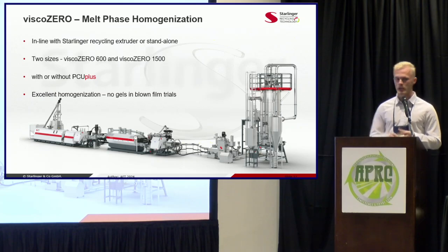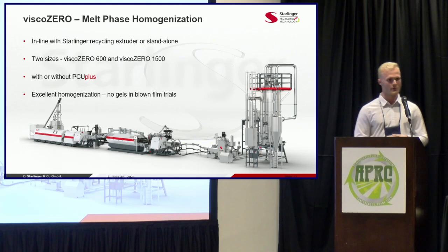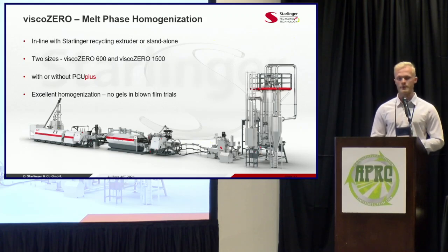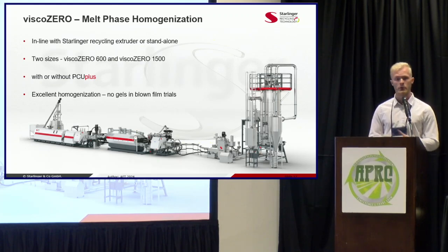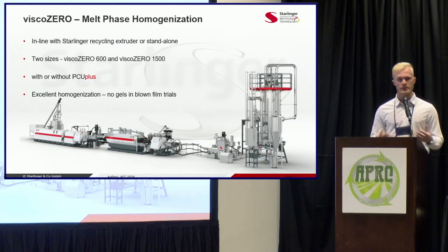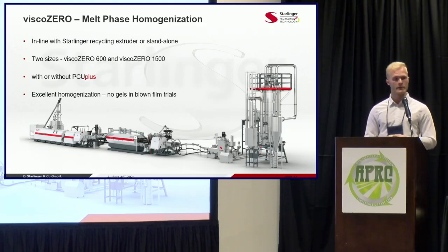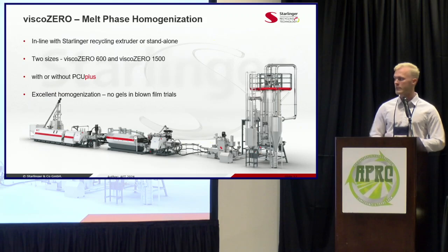And there's two sizes at the moment, the Visco Zero 600 and the Visco Zero 1500. And of course, that corresponds with the outputs. So the 600 is about 600 to 800 kilos per hour. And the 1500, of course, depending on material type and melt flow, is anywhere from 1100 to 1500 kilos per hour. And this solution can be sold standalone as well. So if there's an existing extrusion system and that's something of interest, then there can be discussions there too.